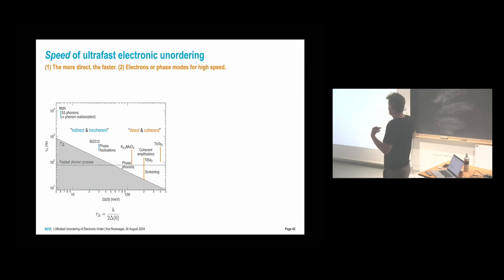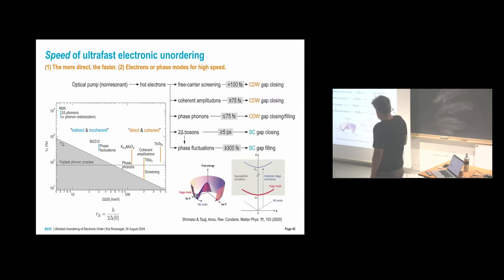And if you then bring all together, here these various systems, here's the gap size, and here are the time scales. Then you find here the indirect, incoherent processes in the superconductors on the left side, at rather slow times, far away from the fundamental scale of the energies of the gap and the corresponding time scale. Whereas in the charge density waves, in particular when you think of these phase phonons or the electronic screening mechanism, you can approach the fastest time scale. So if you think of a switch, you should go for a charge density wave system. And here again, this illustration, the excitation path, hot electrons, different mechanisms, and these can be fast or slow.